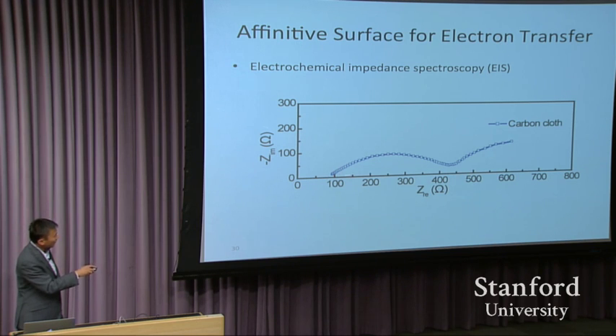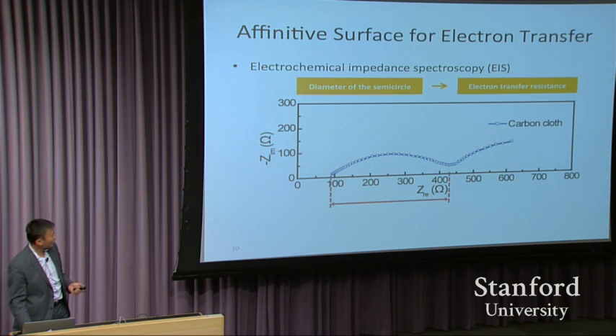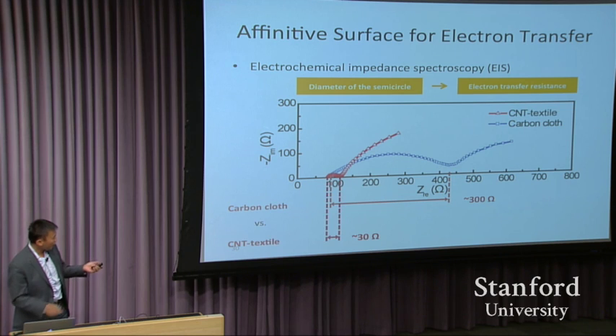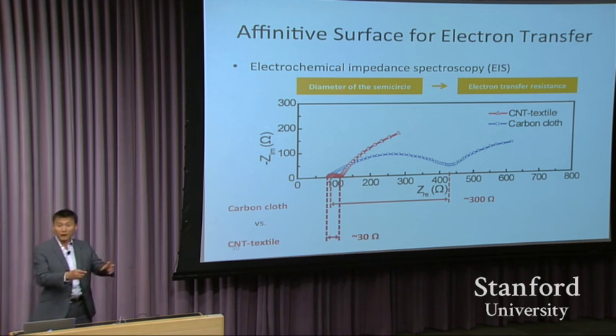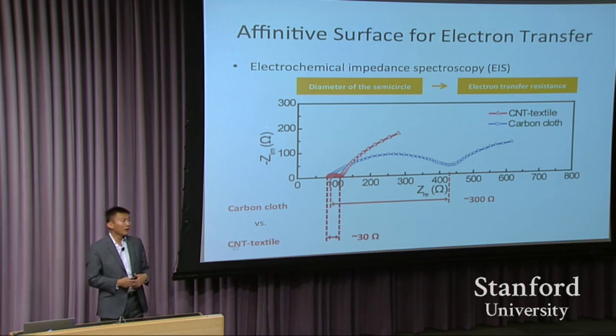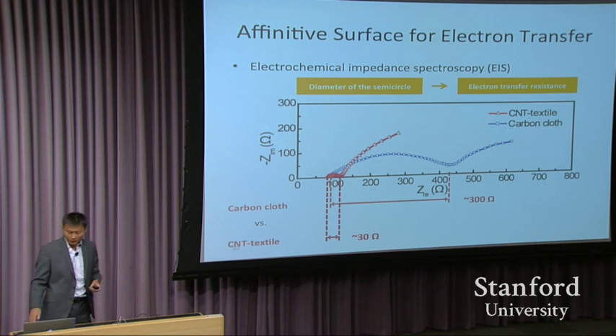The diameter of this semicircle from 100 to 400 gives you 300 ohm for the carbon cloth. But for our case, the semicircle is so much smaller, so this becomes about 30 ohm. You have 10 times less resistance. That's because of strong attachment, very strong attachment of this microbe with your electrode.